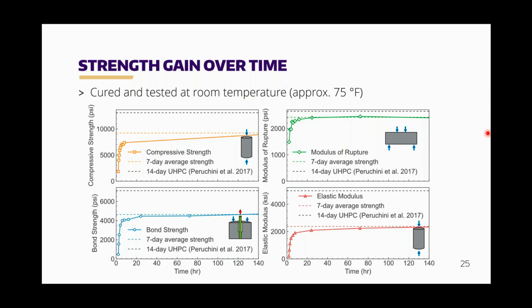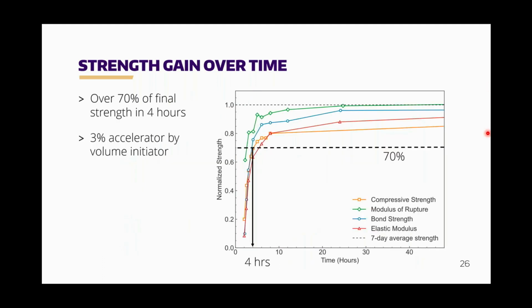Awesome. So here we normalize all of these plots. The 1.0 normalized strength is that of 7 days. And so again, we're seeing with that 3% accelerator cast and cured at room temperature, it takes about 4 hours to reach 70% of the final strength.